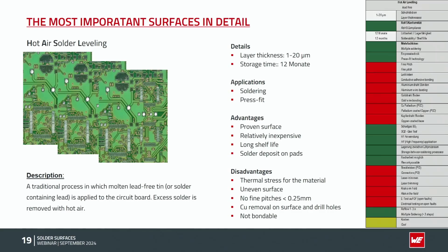We have long shelf life. It's relatively inexpensive, but of course it's a high stress for the material. We have an uneven surface. It's not fitting for fine pitch applications.